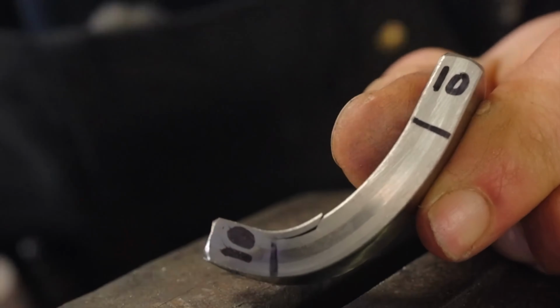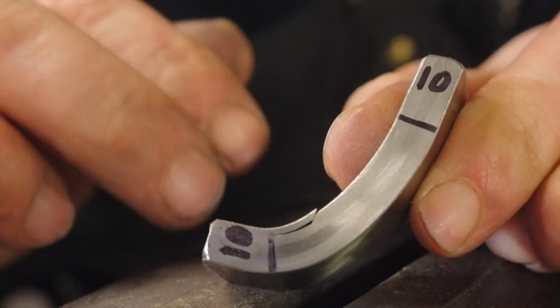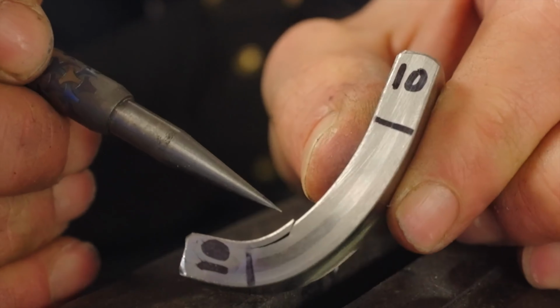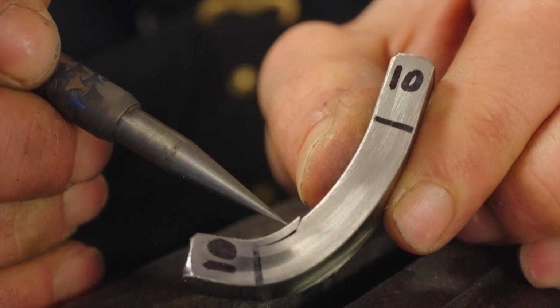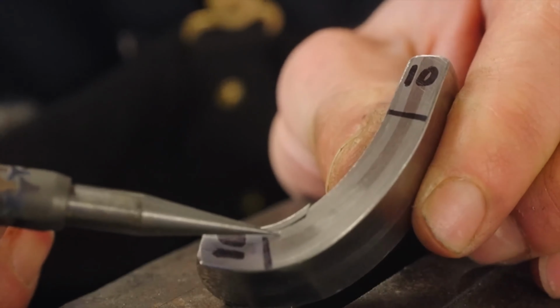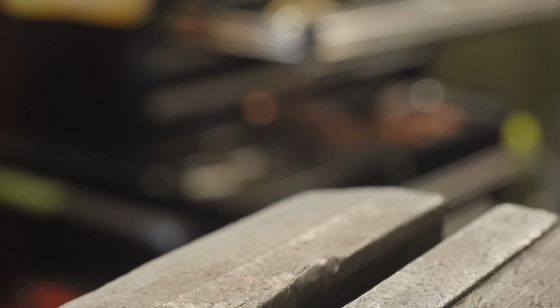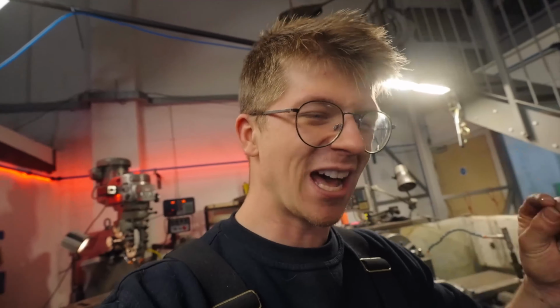Yes! It didn't break at the joint between the steel and the titanium. That is a break at the grade 5 titanium interface with the grade 2 titanium layer. And that was hard to pull. Unbelievable. I can't believe it. I think we've just done something really cool. I think this means we can try making a knife from it. A titanium-clad steel core knife, and is stronger than hardened steel and stronger than just titanium.